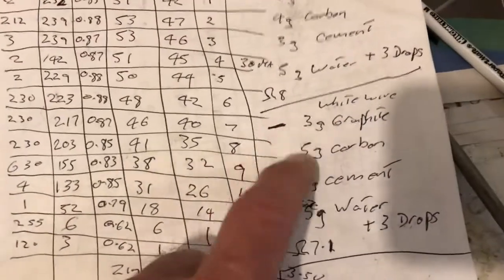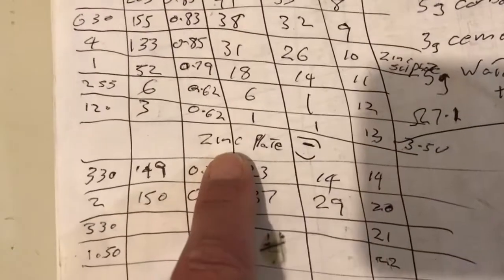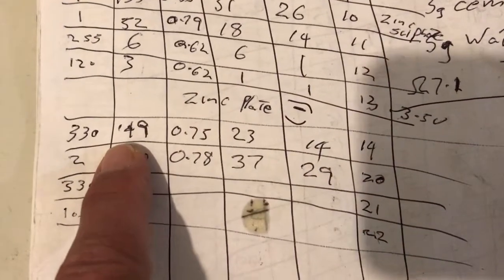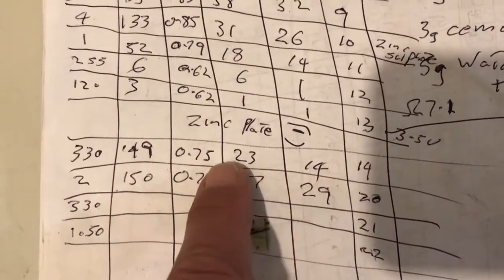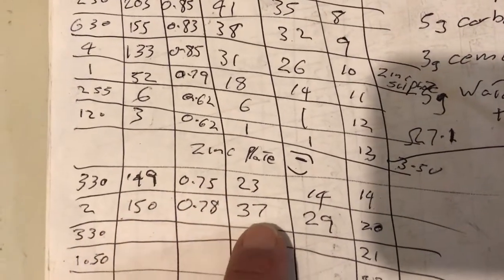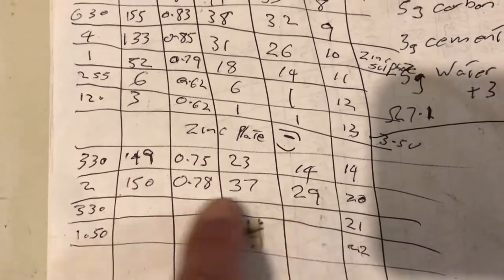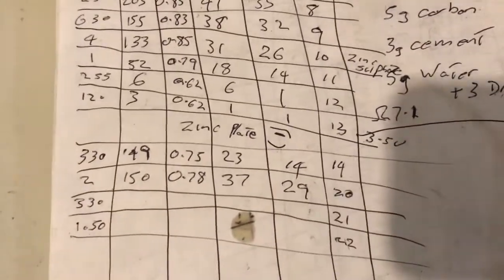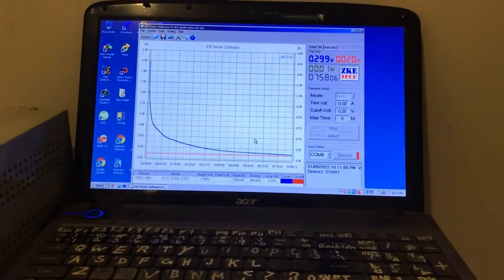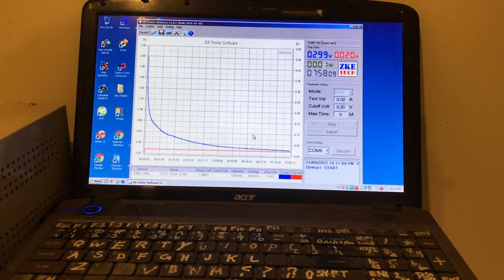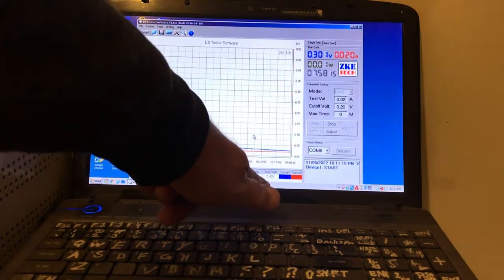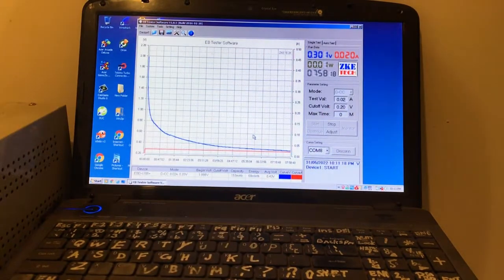So something with the mesh inside the negative, because I swapped it over with a zinc plate and the cell came back okay for the first run and the second run. And the third run it failed, so I pulled the zinc plate out, left it out overnight, and it's on a low cutoff voltage. We're at 159 milliamp hours and 68 milliwatt hours, so its average voltage is only 0.43 and it's still at 0.3 volts. It's nearly 8 hours run time.